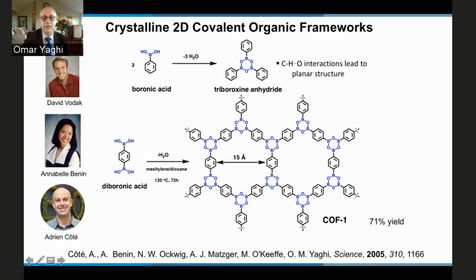And what allowed us to do that is that this reaction has as byproduct water, and we run it in a sealed tube. And by controlling the pressure of water in that tube, you can control the reversibility of this reaction and therefore be able to control the crystallization of the material. And of course, the solvent system that you use is absolutely essential. So are the temperature and how long you wait for the crystals to form.